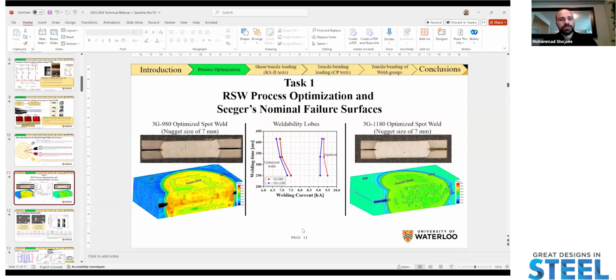In the case of the 3G980, what is interesting to mention is that in the subcritical regions around here, we have some secondary hardening. But in the case of the 3G1180, we have softening in the subcritical HAZ region. The fusion zone of the 980 is slightly harder than that of the 1180. That's, I'm guessing, mainly because of the higher carbon content of the steel, which is increasing the hardenability of it.